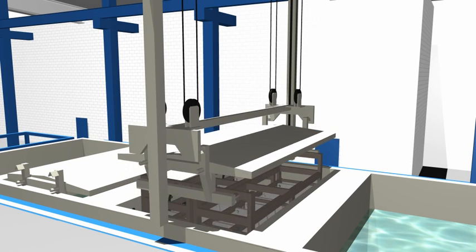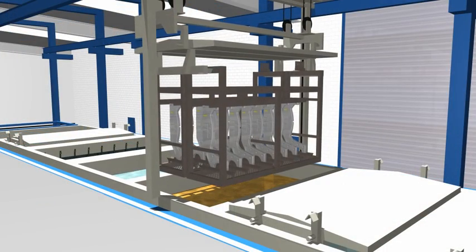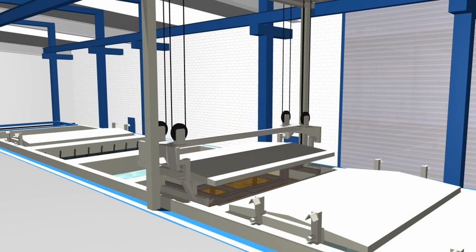After having passed through a number of additional immersion cleaning basins, the basket is introduced into the pickling basin. In this basin, alloyed or slightly alloyed parts are immersed into a sulfuric acid-based metallic mordant. This pickling process derusts, descales, and pickles the parts and creates a highly reactive metal surface. Following additional cleaning processes, the surface of the parts is activated by immersion into a special titanium phosphate liquid. This treatment causes increased nucleation on the metal surface and leads to quicker layer formation of smaller crystals with a lower layer weight.